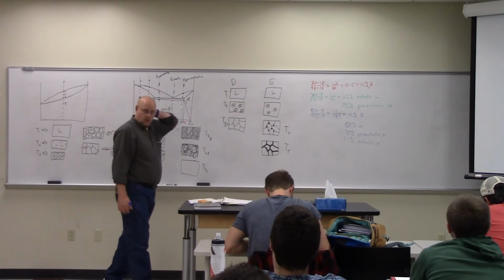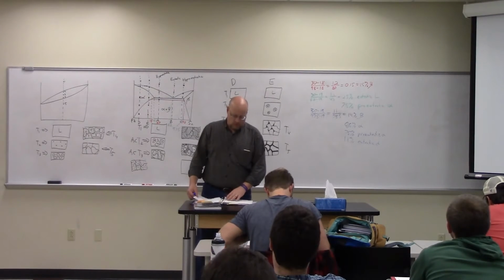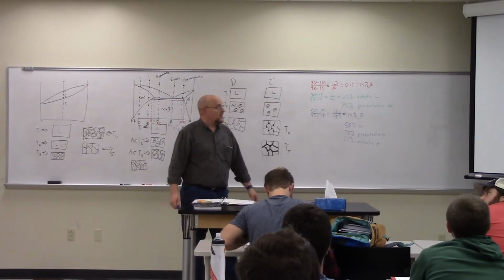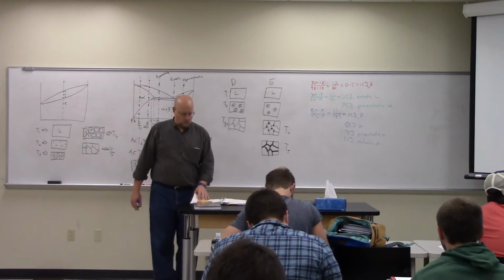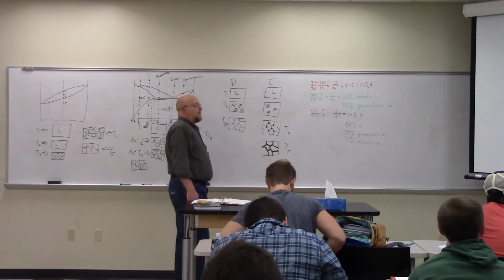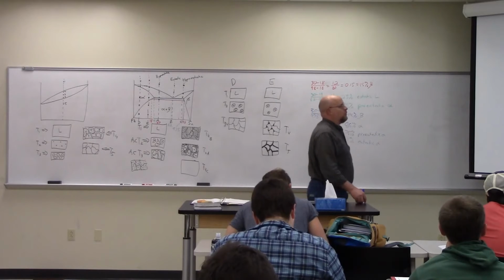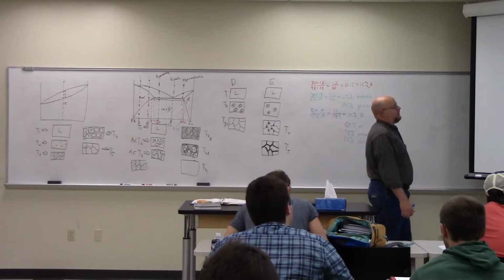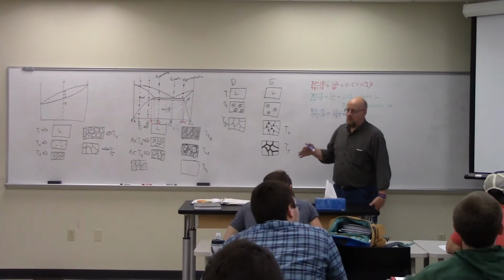So you have to walk yourself through it one step at a time. So let's do an example. Calculate the amount of pro-eutectic gamma. So there's the word pro-eutectic. Calculate the amount of pro-eutectic gamma that is formed at 1,000 degrees C in the slow cooling of 100 kilograms of 3.8% carbon white cast iron. So you have a large percent carbon, it's cast iron.